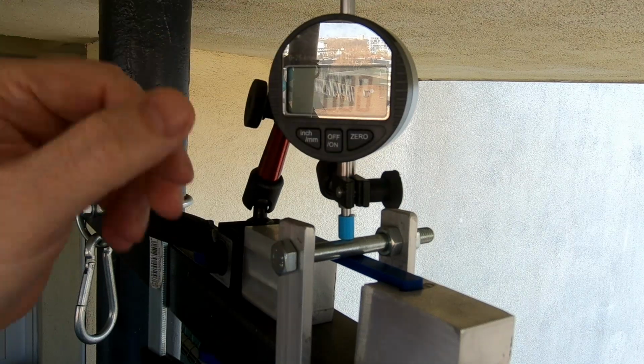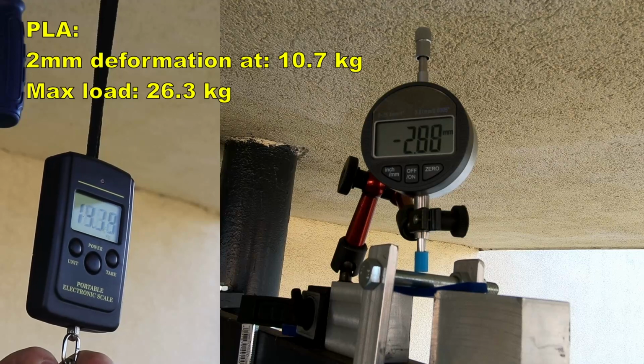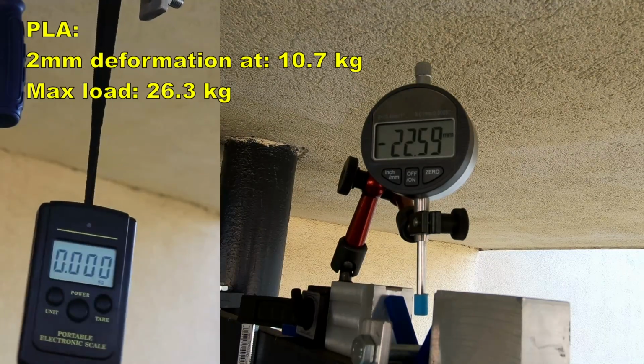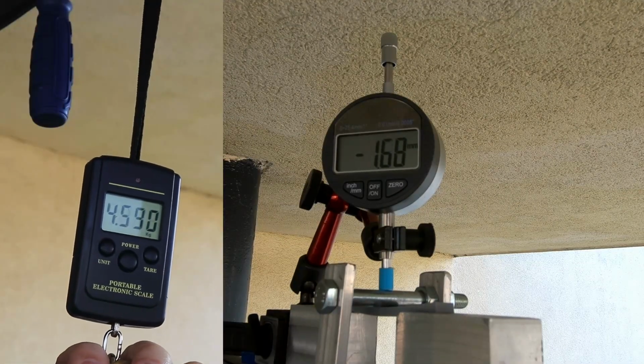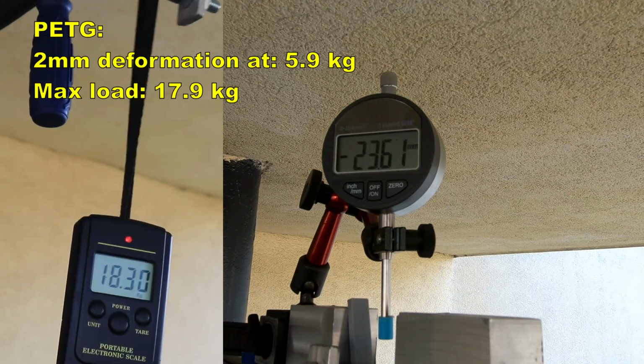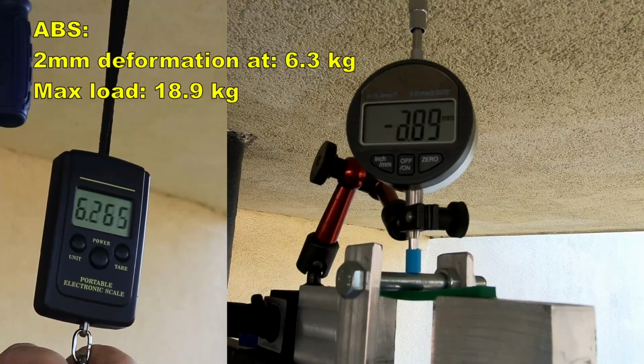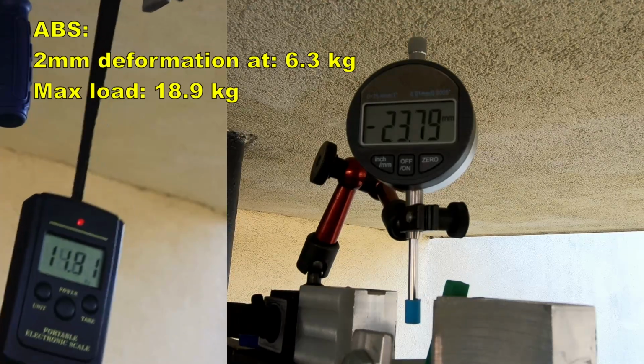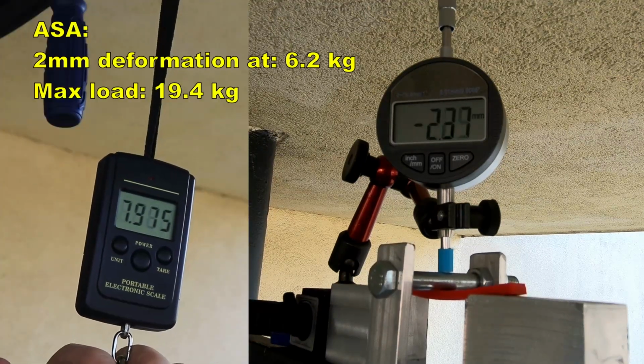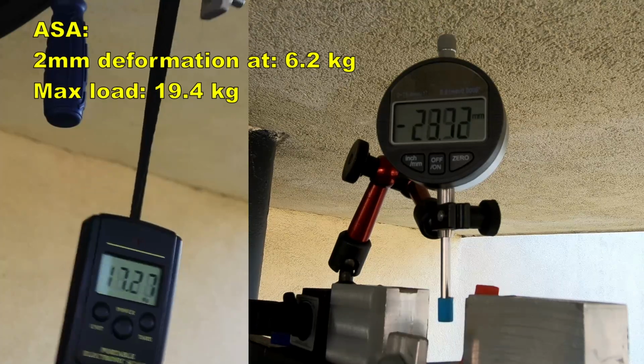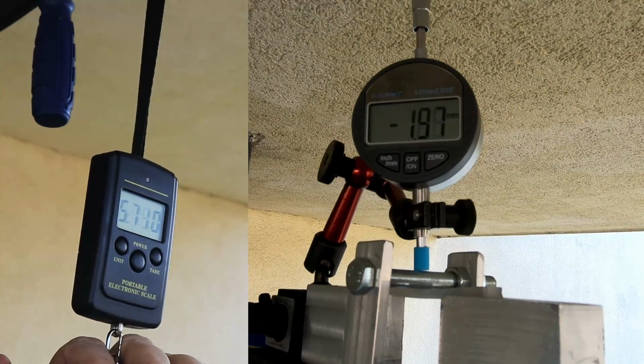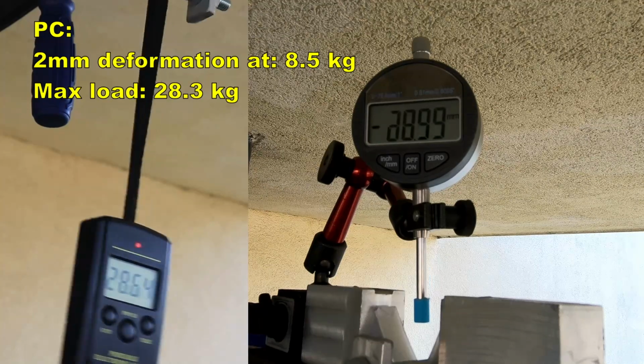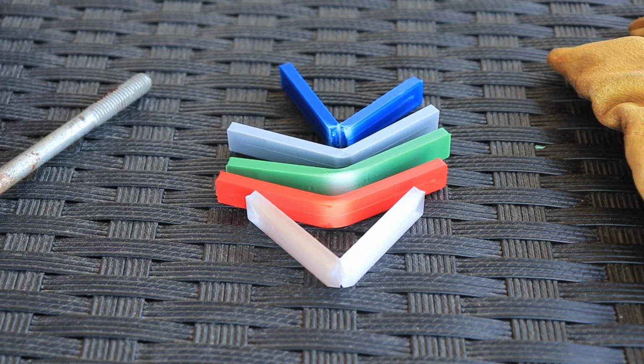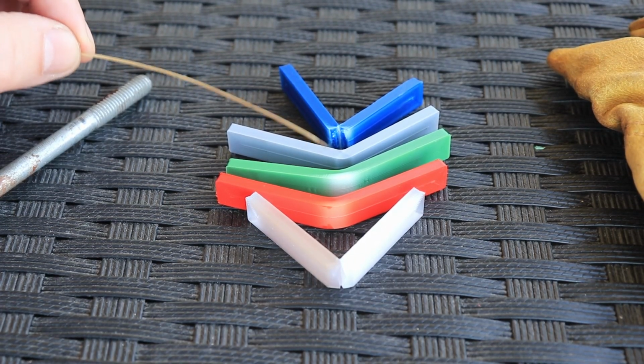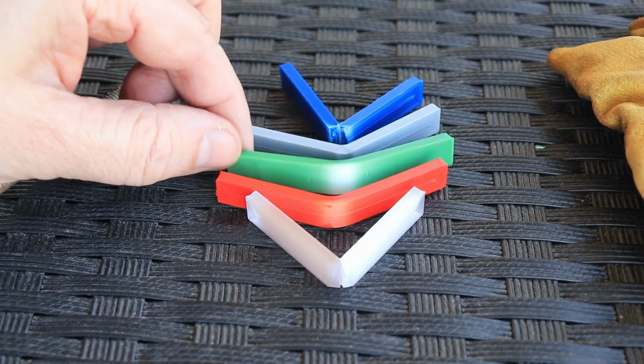This is the 3-point bending test. Distance between supports is 50 millimeters, and I want to record the load at 2 millimeter deformation and the maximum load. And after the test, only PLA and polycarbonate broke completely. The PETG, ABS and ASA just deformed. And again, watch this white area on ABS.